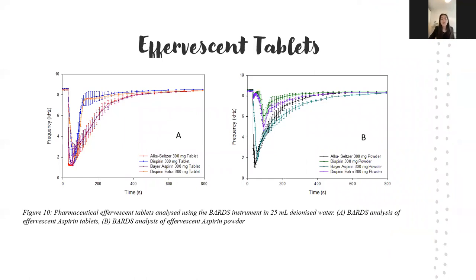So 300 milligrams of tablets were sampled and analysed in both tablet and powder form. And this weight was selected for the resulting resonance frequency minimums to ensure it satisfied the Crawford equation. So if our frequency minimum goes below 1, it doesn't satisfy the Crawford equation and therefore is not BARDS compatible. And the tablets in this case are very large, they're 4 grams. So as you can imagine, the F-min is very low when you analyse the full tablets and causes a huge amount of oversaturation of our solution. So figure 10 shows a BARDS analysis of aspirin-containing effervescent formulations. Alka-Seltzer and Bayer aspirin are both marketed by Bayer and perform identically in solution.